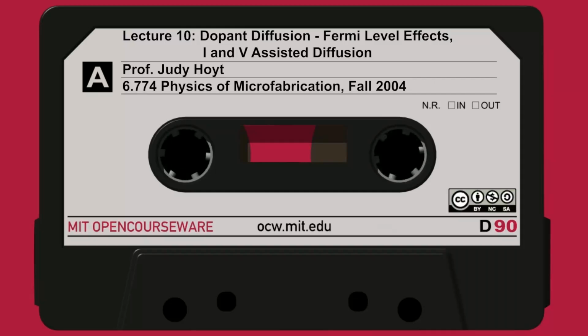On slide 31, there's a famous effect people call emitter push. Again, they thought of lots of reasons to explain this. What is emitter push? Well, when you're making a bipolar transistor, you have a high concentration emitter, could be phosphorus or arsenic, and then you have a more lightly doped base, and then you have a more lightly doped collector. What people observed is wherever the emitter, the phosphorus, was being diffused, right underneath it, the boron base was pushed out, almost like the emitter was pushing the boron to diffuse faster. Far away from the emitter, over here, it didn't diffuse quite so much, but underneath it diffused quite a bit. And again, there were a lot of models people came up with to explain this.